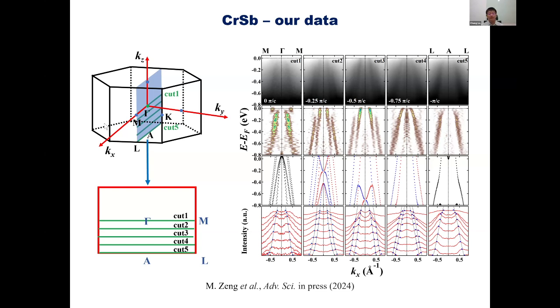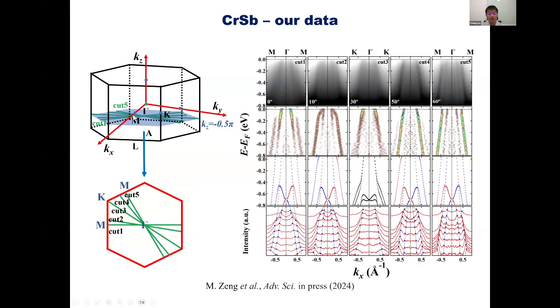For the in-plane directions, we also cut from cut 1 to cut 5 here. Along cut 3, we will not have spin splitting by definition, but in cuts 1, 2, 4, and 5, we can see spin splitting here. So these are quite clearly spin splitting.